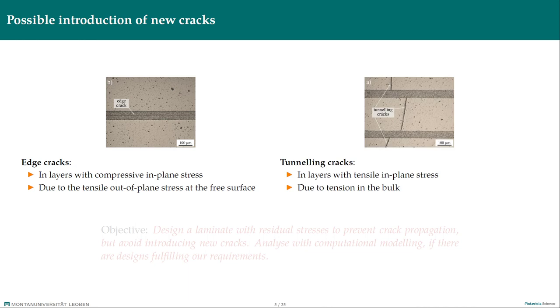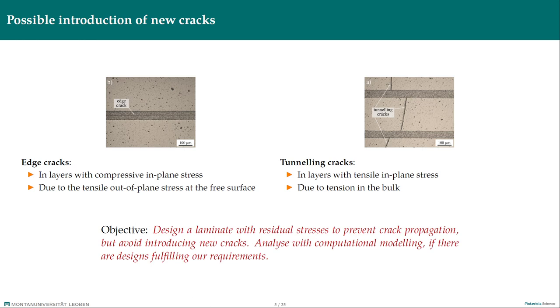Second kind are so-called tunneling cracks which appear in layers with tensile in-plane residual stress. They are commonly oriented perpendicularly or close to the perpendicular orientation to the layers and extend through the thickness. The initial location cannot be known a priori but it is reasonable to assume that more likely a crack initiates deeper in the bulk rather on the free surface where the residual stress decreases approximately by one-third. Hence we formulate our objective as: Design a laminate with residual stresses to prevent crack propagation but avoid introducing new cracks. Analyze with computational modeling if there are designs fulfilling our requirement.